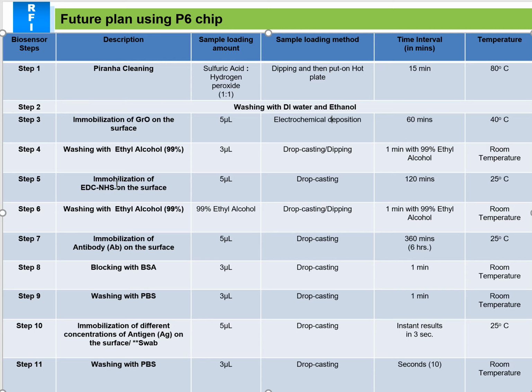So it's washing, then EDC NHS, then afterwards washing again, and then immobilization of antibody, and then BSA as a blocking method so that unwanted antibody peels off from the surface. Afterwards we use PBS for the normal washing, and then we use antigen and afterwards wash with PBS and then measure. It's a serial kind of steps that we have to follow for this process, and for each step we have to measure the capacitance value using the impedance analyzer.